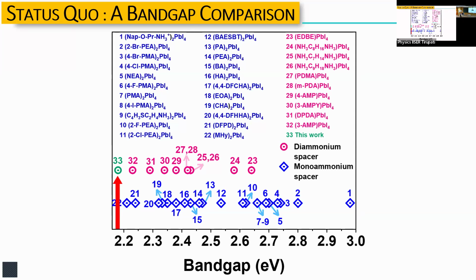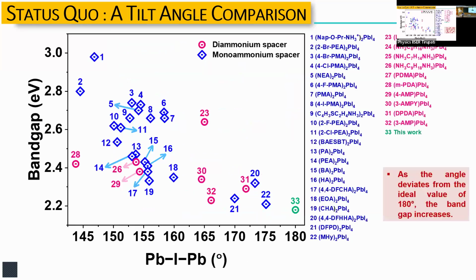So Debashmita wanted to understand this band gap. What is the structural aspect? Because eventually it is the structural aspect that causes the electronic properties. And so what is the structural aspect? And she had some reason to suspect the Pb-I-Pb bond angle is relevant. And so she plotted the band gap of all the literature, including her own, which is sitting over here. Here is the band gap as a function of the angle. And you can see that roughly speaking, as the Pb-I-Pb angle approaches 180 degrees, which is the maximum it can be, because if it tries to be more than 180 degrees, the other angle becomes smaller, right? So 180 degrees is the maximum angle that can be there. As it approaches, the band gap roughly comes down. And there's a very good, easy way to understand that.